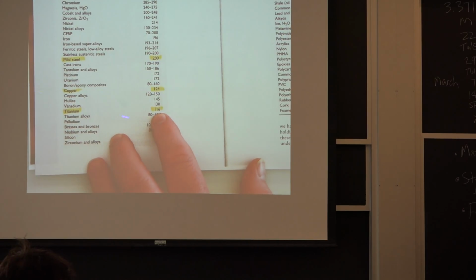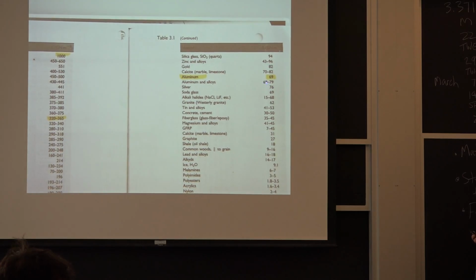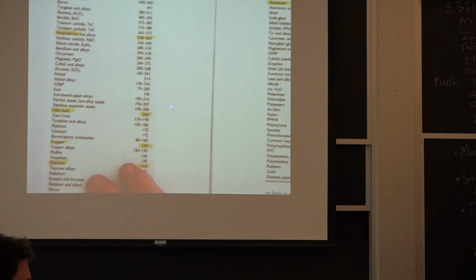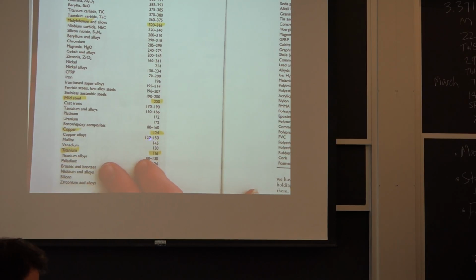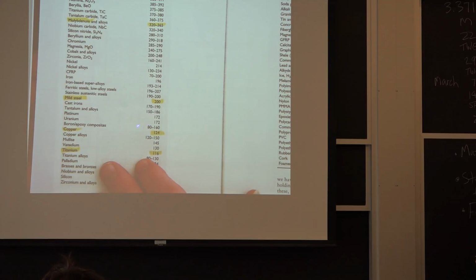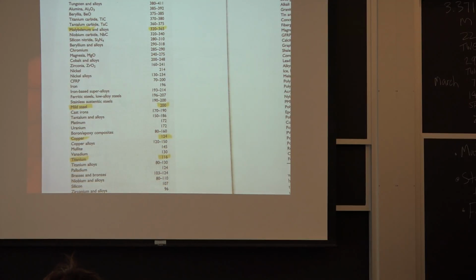Titanium is only 116, and aluminum is 69. Okay, it's only 7% of that of diamond. Copper is 124. It's about the same as titanium. Copper, interestingly, is very crystallographic orientation dependent in terms of modulus.